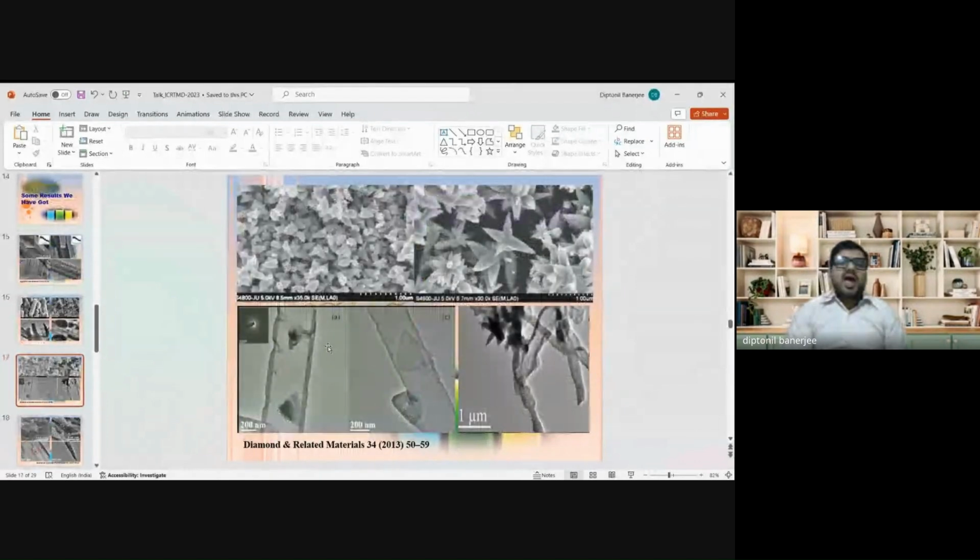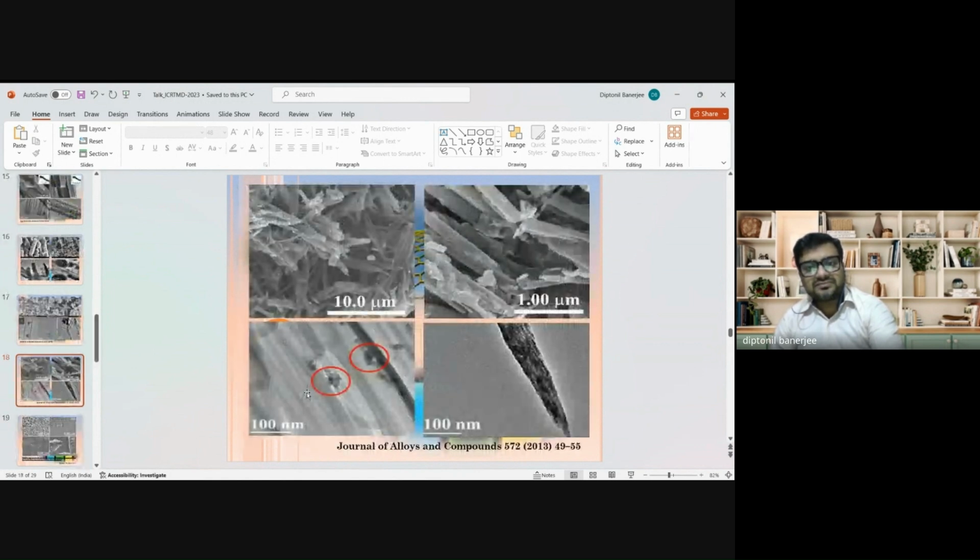And this is the zinc oxide flower-like structure and zinc oxide triangle-like structure that you can see, that is very uniformly attached with the wall of the carbon nanotubes. So in every case, a very well dispersed functionalized sample can be synthesized, which is almost impossible in the case of crystalline CNT unless you go for external functionalization. This is a SnO2 CNT functionalized sample.